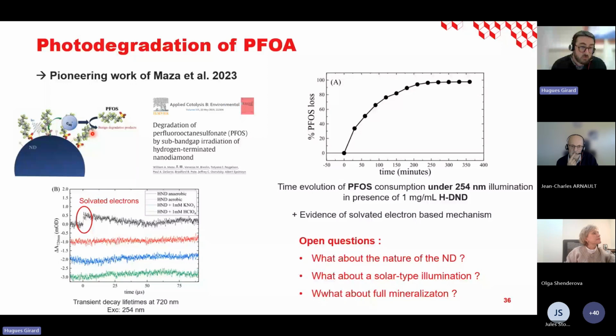they were able to see also some solvated electrons, which confirmed what was previously observed. But the point is that they used these solvated electrons to degrade one type of PFAS, which is perfluorooctane sulfonate, the PFOS, and they used for that a light centered at 254 nanometers, so quite deep UV. And the evidence also that the mechanism of degradation is based on solvated electron mediation to break the CF bonds. And so starting from that, we thought about quite some open questions. Okay, what about the nature of the nanodiamond?